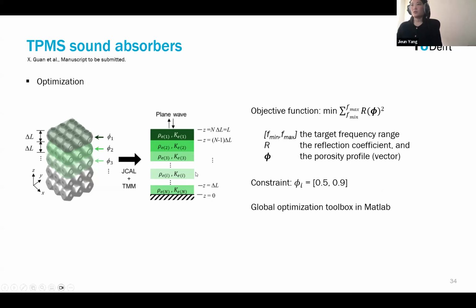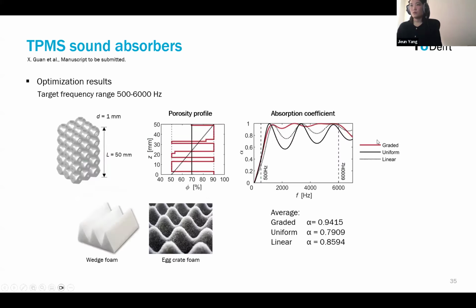And we conducted optimization. The optimization was to minimize the reflection coefficient in the frequency range that we set. And then we also had some constraint on this porosity. And then we used the global optimization toolbox in MATLAB to get the optimal porosity distribution. So this is a result, for the optimization result for the target frequency range from 500 to 6,000 Hertz.